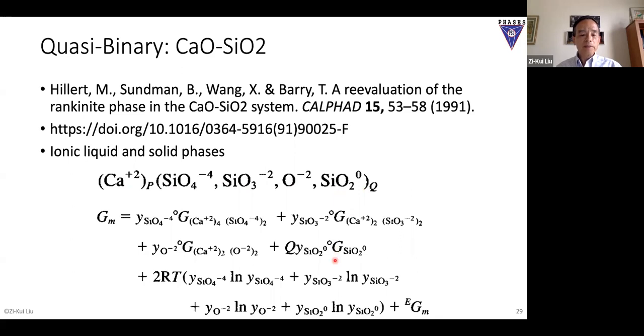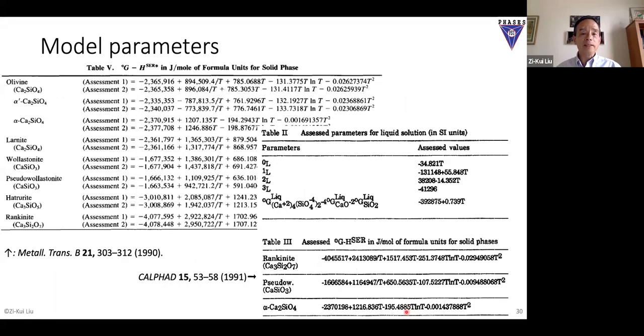And then you have the entropy of mixing in the second sublattice. They have an excess term. So now if you do the model, of course, it becomes very complex now. It's a little bit complex, but the sigma phase is more complex.